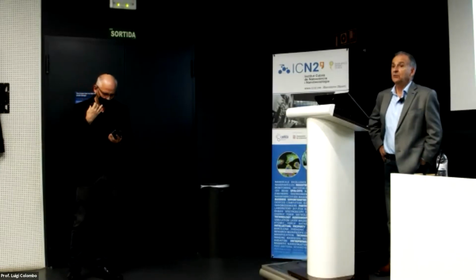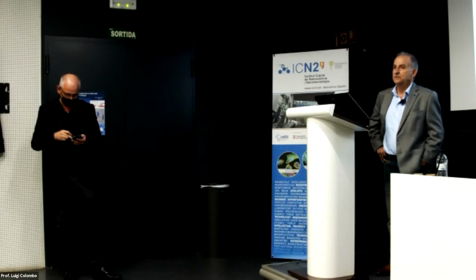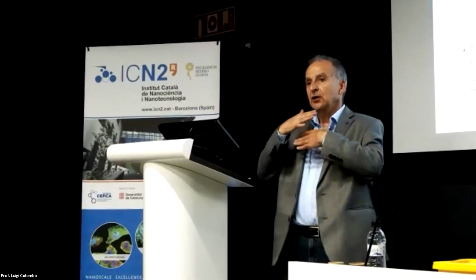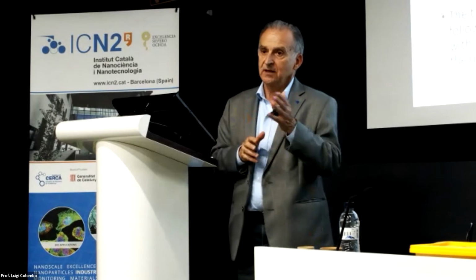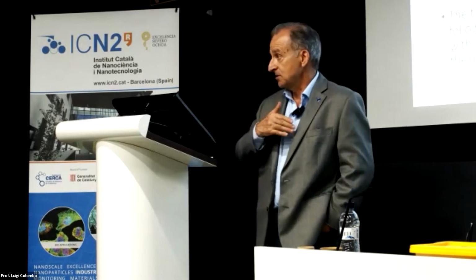Practically speaking, people have found that it's extremely difficult to grow selenium-terminated surfaces that don't absorb oxygen or water or what have you. And so selenides are very difficult. Some of the experiments that we did at UT Dallas, they had to basically coat the tungsten selenide with extra selenium, so that you can then remove it. And so the defect chemistry is quite different. The vapor pressure and the bonding energy are different for the selenides versus the sulfides. Sulfides are actually more stable than the selenides. So in terms of chemical stability, the sulfides are much more stable.